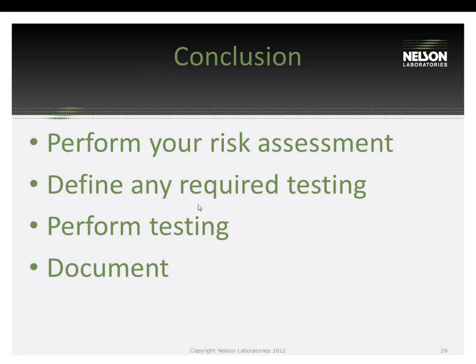Okay, on the slide for F2096, it was mentioned that the package is submerged into a surfactant solution. Is this unique to Nelson? The ASTM method only indicates to submerge underwater. I don't think it's unique to Nelson. My conversations with other ASTM committee meetings, several people use different types of surfactants. What it does is it increases the sensitivity of the test. So I don't think that this is a unique solution to our company.